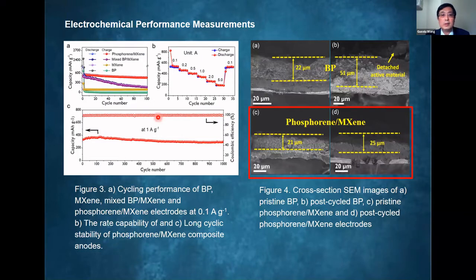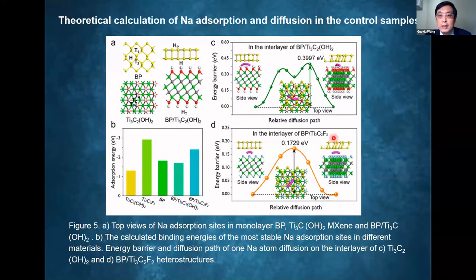And particularly, we can achieve very high rate capability. In this case, at 1 amp per gram current density, we can discharge sodium ion cells for more than 1,000 cycles. And after cycling, we observed the thickness change of the electrode. When you directly use black phosphorene as the electrode, you can find after cycling, the electrode thickness increased dramatically. Surprisingly, when you use the phosphorene MXene composite, you can minimize the electrode expansion to, in this case, just 4 micrometers. And also we did a theoretical calculation.